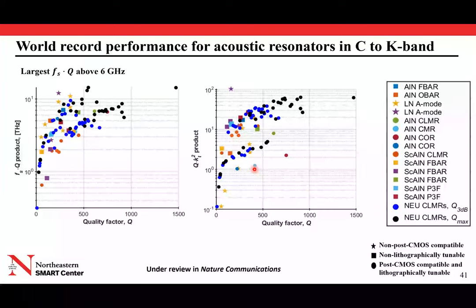And just to give you an idea of the importance of these results compared to the state of the art, what you can see here are some important resonator metrics, like the f·Q product plotted versus frequency. And basically what we want is to be on the top right corner of this chart, right? So we want to have a high f times Q product, but while we scale frequency up, we want to maintain a high quality factor. And as you can see, we are really breaking the boundaries of what was achievable before with these relatively simple structures. And same thing for the Kt squared times Q, or the figure of merit of the resonator technology. You want to be on this top right corner of the chart, right? So you want to have high coupling, maintaining high quality factor at this very high frequency.